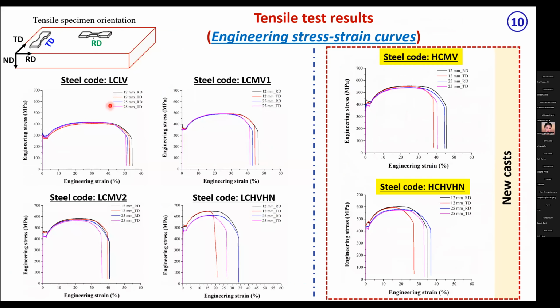Overall, these were the tensile properties. Last time, these were the properties that I presented here. These were low carbon, high vanadium, high nitrogen steel, which showed quite a high strength. You can see the yield strength level very conveniently more than 450 MPa and even crossing 500 MPa. This time we got a good strength in our high carbon, high vanadium steel, but strength was not that high, maximum around 460 MPa. And in this steel, high carbon, medium vanadium, the yield strength is around 400.